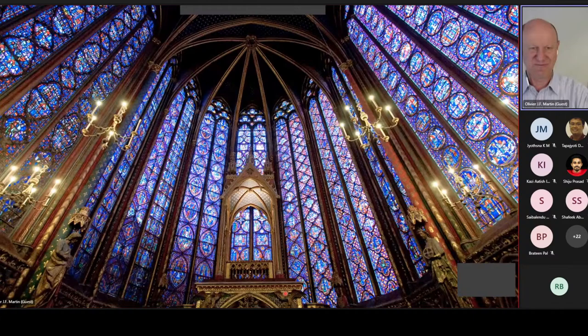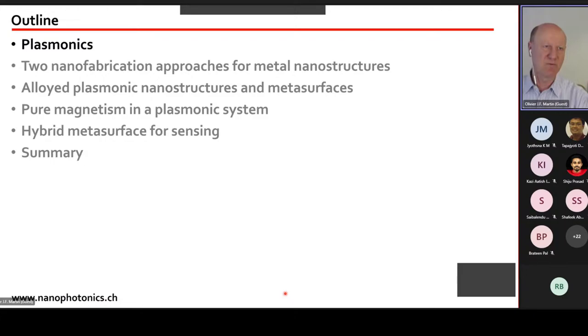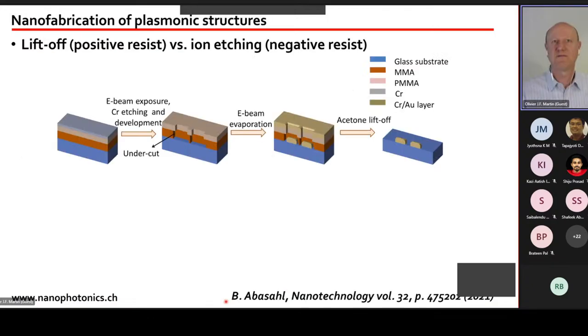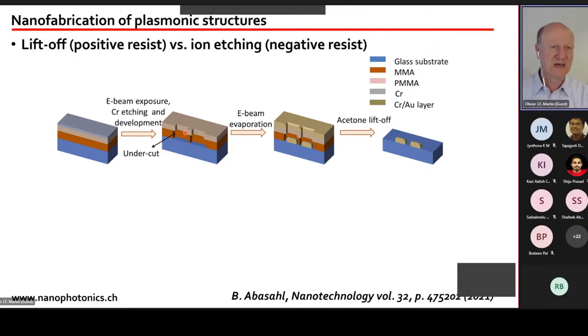Now let me delve into nanotechnology, since we need very small metal structures. I'd like to share a recent paper comparing two nanofabrication techniques for plasmonic nanostructures. The first — typically the standard approach — is liftoff using a positive photoresist. We write very small structures with an electron beam; exposed regions dissolve upon development. We then evaporate gold everywhere, and finally dissolve the remaining resist, leaving only the nanostructure on the substrate.